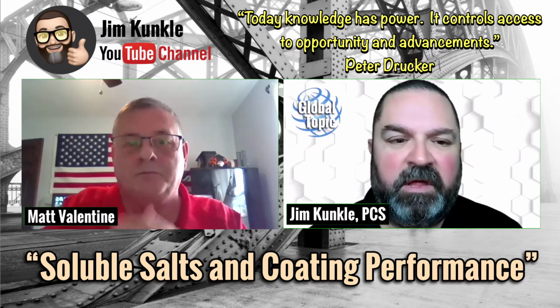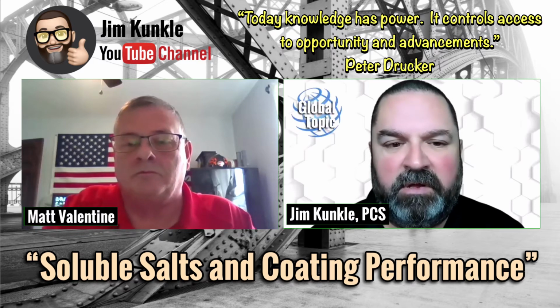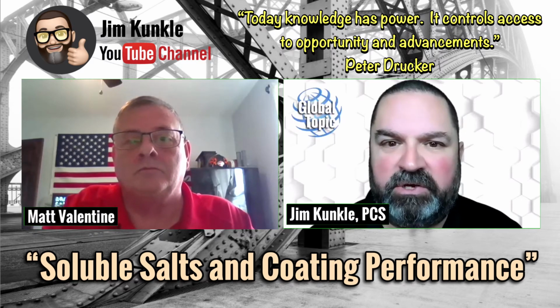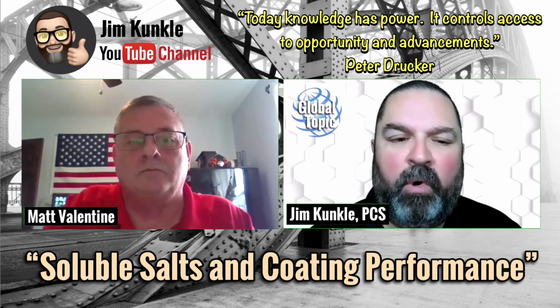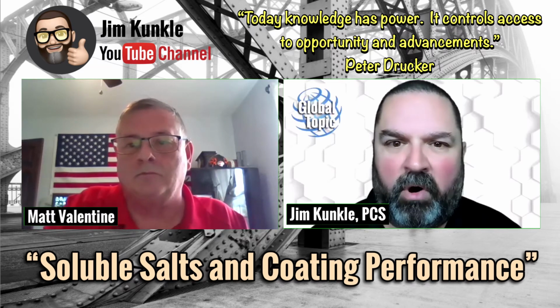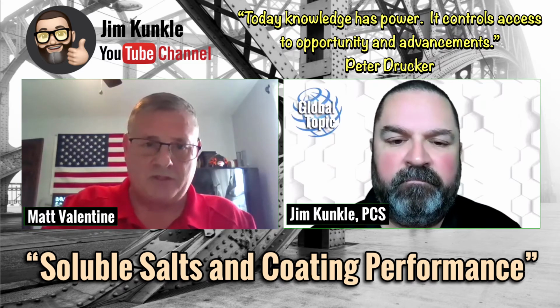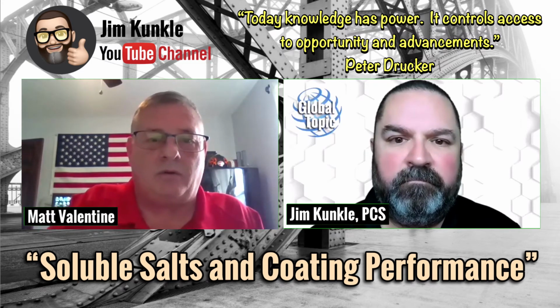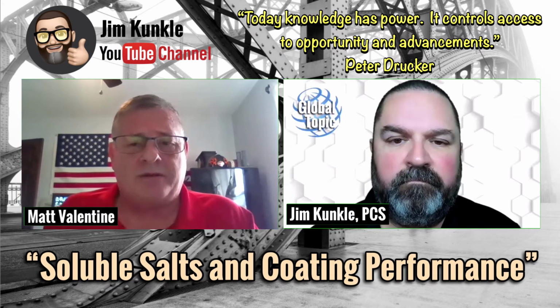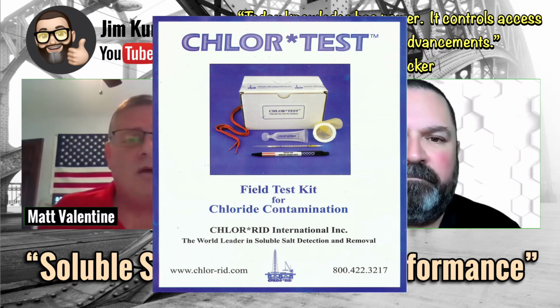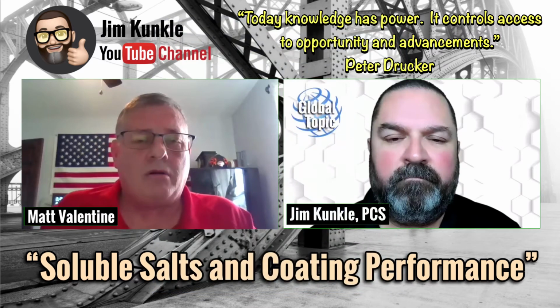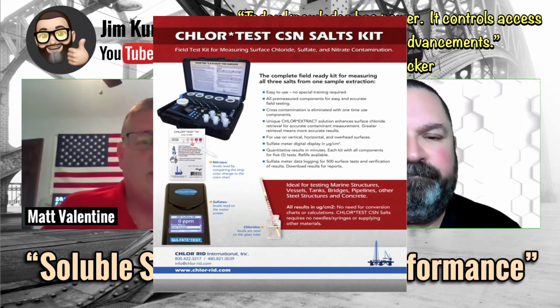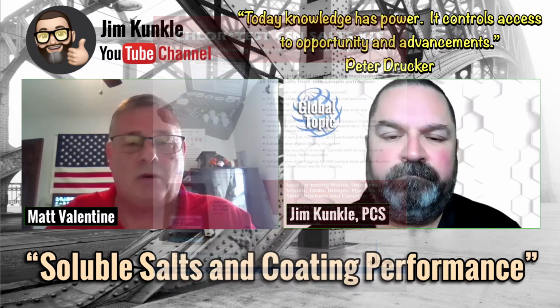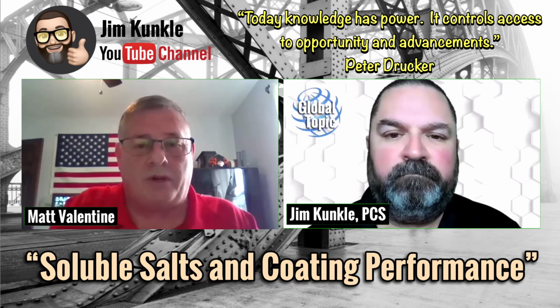So once testing has been done related to soluble salts, and it's been determined that the steel substrate will need additional cleaning for the soluble salts, what can be done with process and product solutions to clean? Well, first of all, the testing is critical. There's varying ways of testing. There's the Bresle test, which is a conductivity test. And then the other tests out there are our test kits, which are ion specific. So you want to know what salt you're dealing with and how much you're dealing with. Our test will give you an actual reading of parts per million.